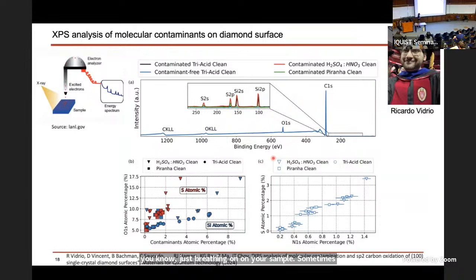And we found a correlation between the oxygen percentage and the contaminants' atomic percentage. Furthermore, we found that a byproduct that is likely one of the culprits is ammonium sulfide, which is a byproduct of one of the treatments that the community uses, which is sulfuric acid on the diamond surface. So we found ways to get around that by doing a more rigorous rinsing and cleaning to clean up all of that.